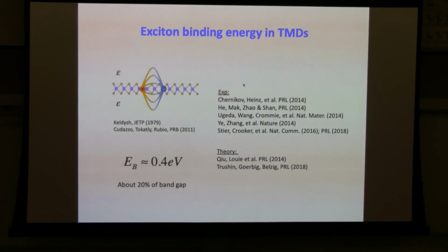Okay. So how big is the exciton binding energy? And I think that was first measured by Tony in 2014. So let's first consider the optically excited excitons in monolayer TMD, where we have an electron and a hole in the same layer. Because the electron and holes live in 2D space, the Coulomb field lines that are responsible for binding this pair actually live mostly outside of the plane. And the dielectric constant outside of the plane is very small, so the Coulomb attraction between the electron and hole is weakly screened. As a result, the binding energy for the exciton is very large. It was experimentally measured to be about 0.4 eV, 400 millielectron volts, compared to the band gap, which is about 2 eV. It's about 20% of the band gap, so it's a substantial number, a very large binding for a semiconductor like this.